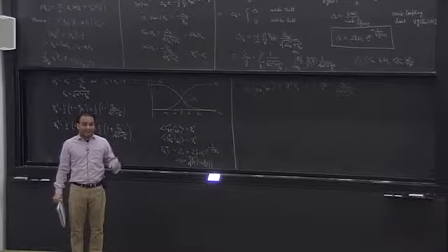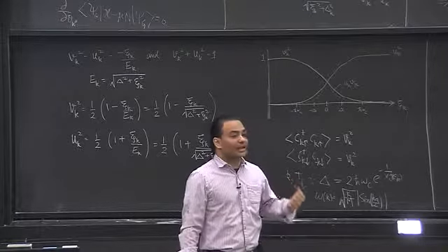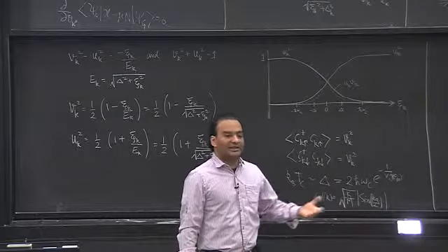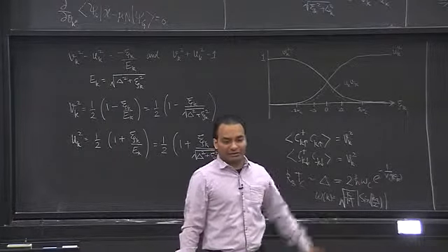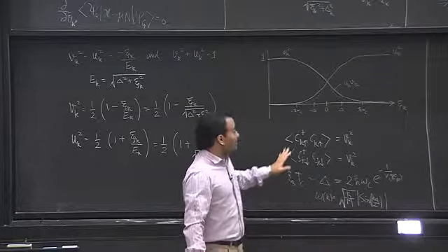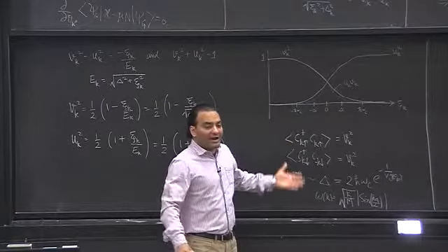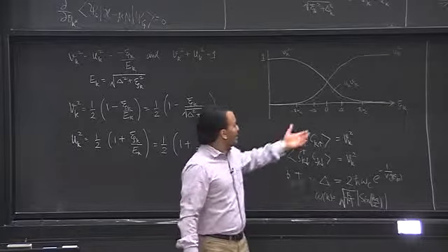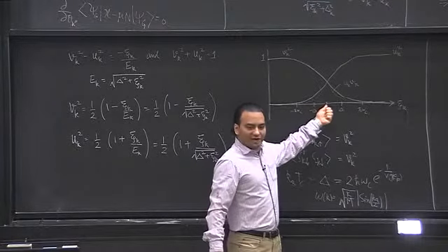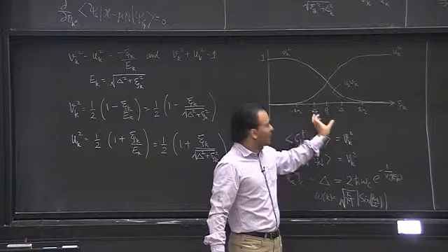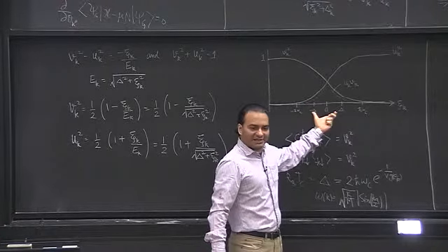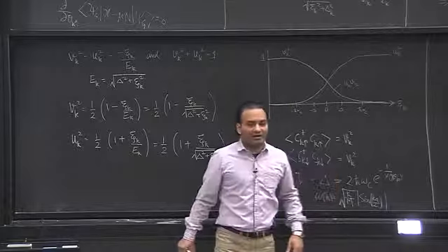So when you go through a phase transition, if this phase transition is related to breaking a symmetry, then you can always find an order parameter that is finite in one phase and zero in another phase. So if I'm looking for an order parameter, this might do the job because this is only finite at the Fermi energy and over this new energy scale delta, and it vanishes at all other energy scales.